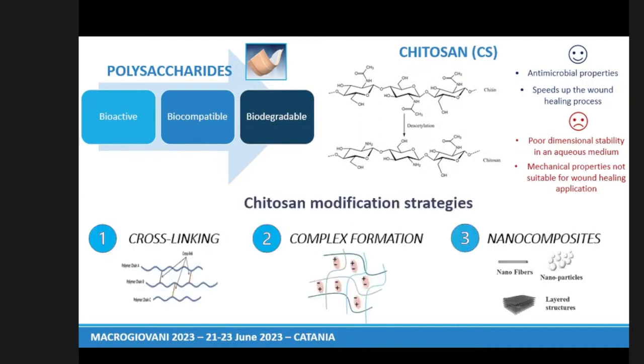In the first case, we have the possibility of cross-linking chitosan through the use of covalent or ionic cross-linkers. In the second case, we can create a complex through the interaction between chitosan and anionic polymers. And in the third case, we can create a nanocomposite material through the introduction of nanofillers in the chitosan matrix. In our case, we decided to create a bioactive dressing using a cross-linking process.